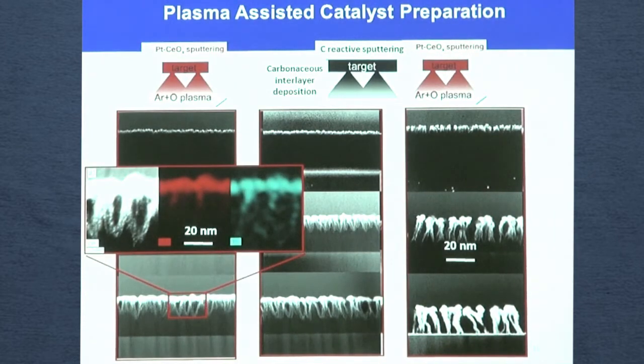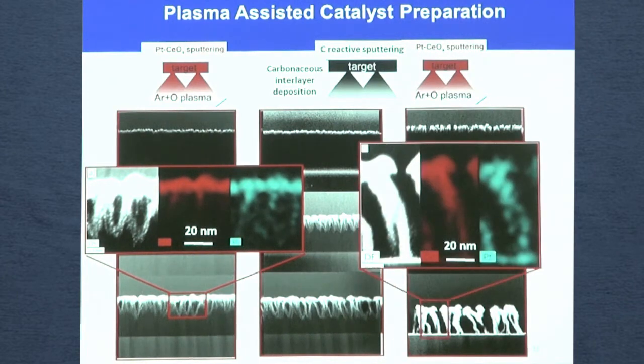Well, if we check how it looks, in this case, you can see this is the hole. So this is a TEM image with EDS, coated with a catalyst, and in the other case, you can see that it's etched down to the silicon substrate. And we have, again, the platinum image, ceria, and it's a dark field image from the TEM.